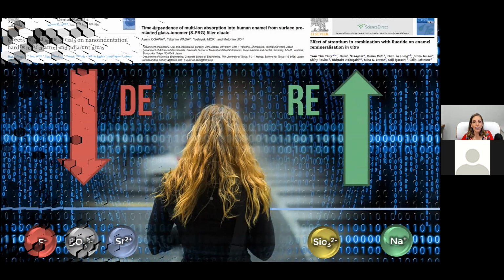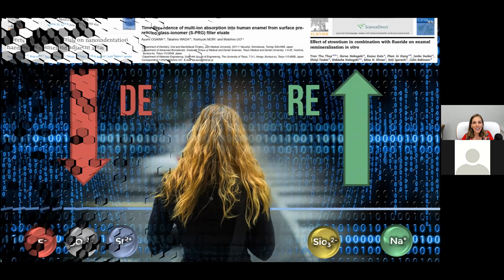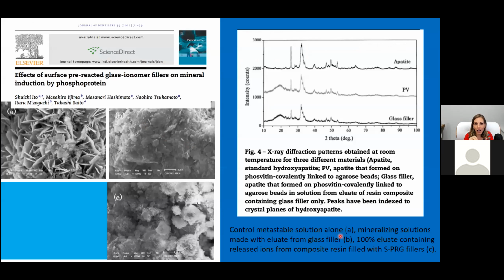Here, this study used a dentin protein model to induce mineral formation after incubation in a solution with and without S-PRG. And the S-PRG fillers significantly reduced mineral induction time. It was faster. And they could observe larger apatite crystals with the S-PRG fillers when compared with the control.